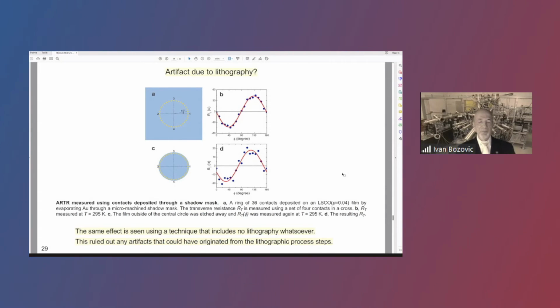It's the same sin 2 phi sinusoid as we see in films that were lithographically patterned into a sunbeam. We have done this with films which were square. We etched away the outer perimeter to make it a disk, and we have done this with bulk single crystals, so they're not even thin films. And we always see the same effect.